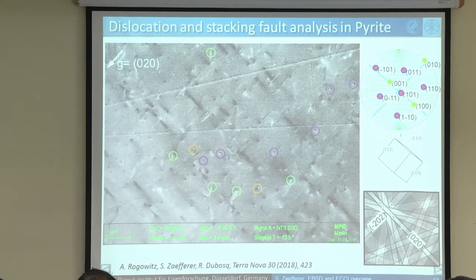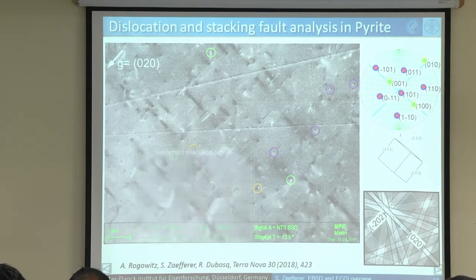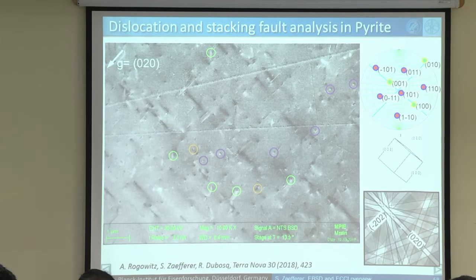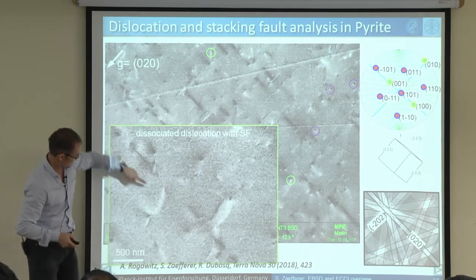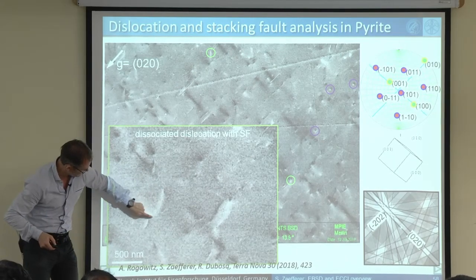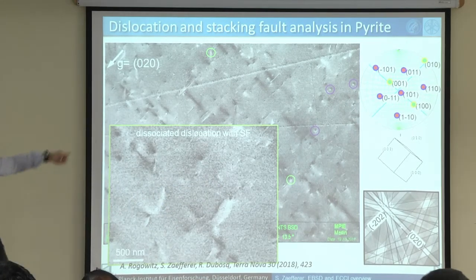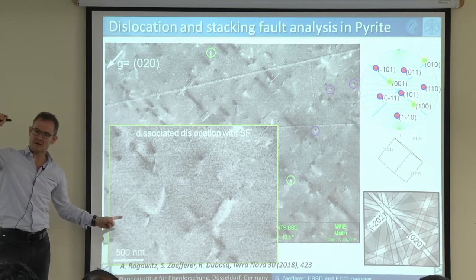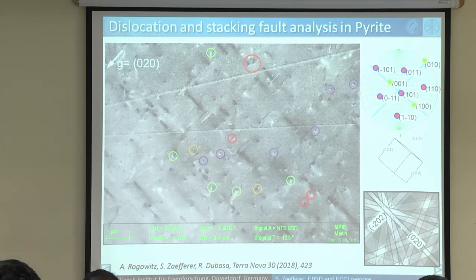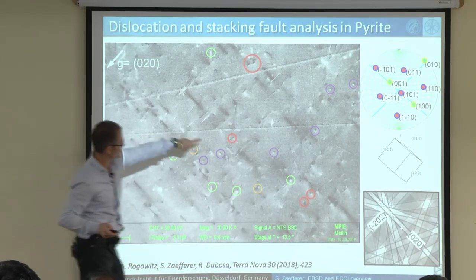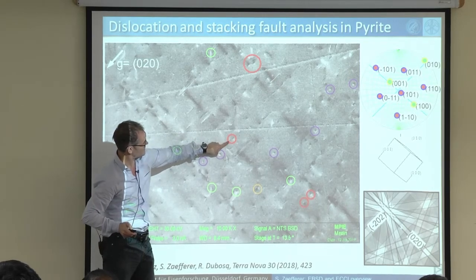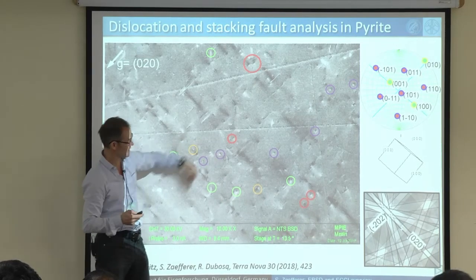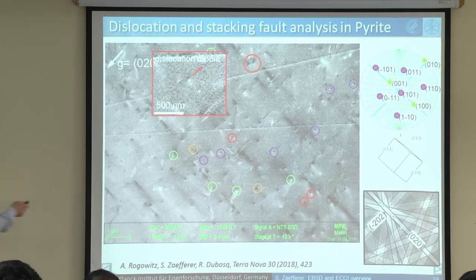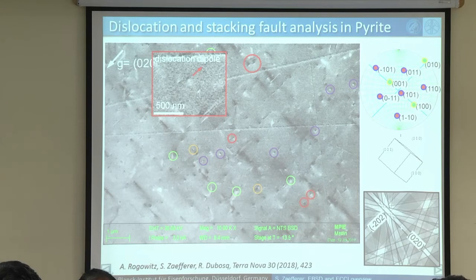Then we have this feature here, these little ones, green. They are, that's difficult, not yet understood. They have a black-white contrast and then this tail here. Always black-white and the tail. We imagine that this is an inclined 110 slip system. Then we have these ones here. This is super interesting, this one here. You see white-black, black-white, coupled close together. So is it better visible there? I don't know. But this is a dislocation dipole of a plus and a minus dislocation.